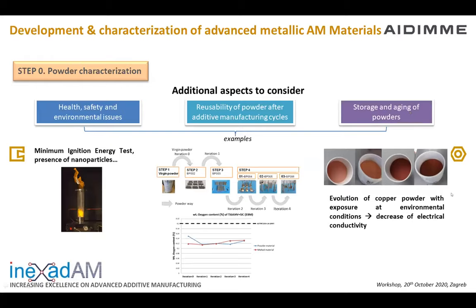Here you can see the description, for example, of this. This is a pure copper again. And you can see here the evolution of the powder with the exposure to environmental conditions. You can see the difference of the color, and this is translated in a decrease of electrical conductivity of the final part. So you need to control that your powder is always in the same condition.